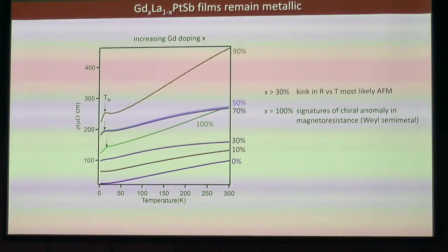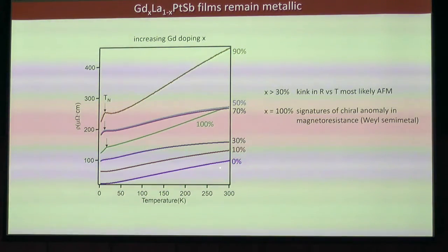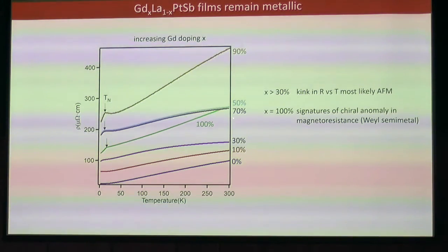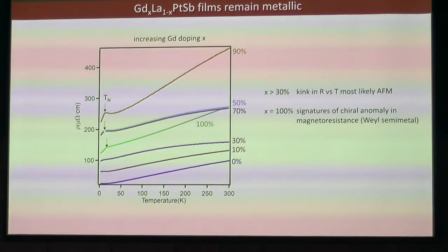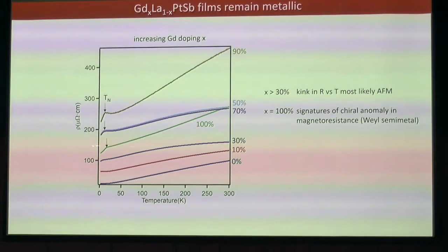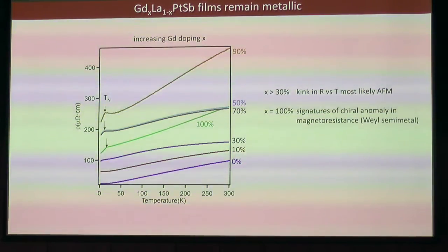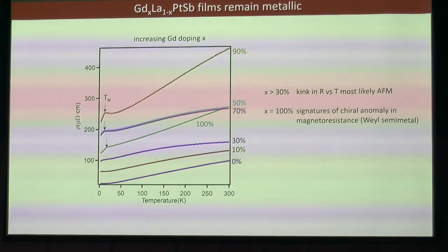Okay, so here's the lanthanum platinum antimony, this baseline compound. As you increase the gadolinium doping, the resistivity goes up and the curves get a little bit flatter. We see some onset of a phase transition right here. We think it's an antiferromagnetic transition because we know gadolinium platinum antimony is antiferromagnetic. But unfortunately, throughout the entire range, all the samples were metallic. So perhaps not good enough there. Maybe we have a little bit more room if we push beyond 95% doping. We don't have that much room left.